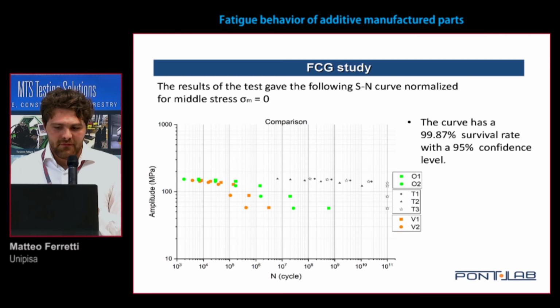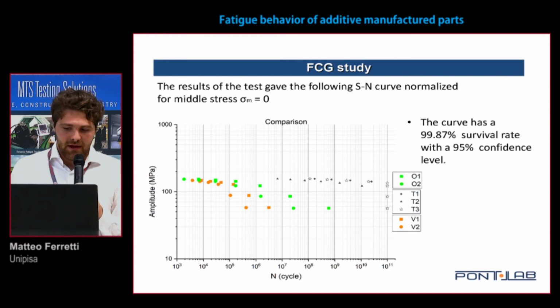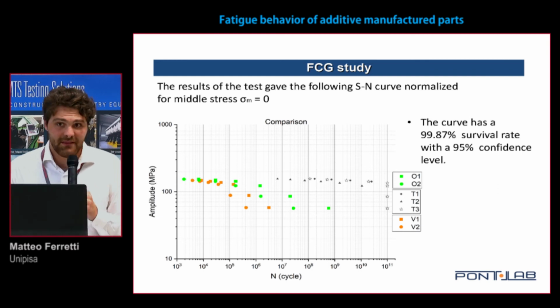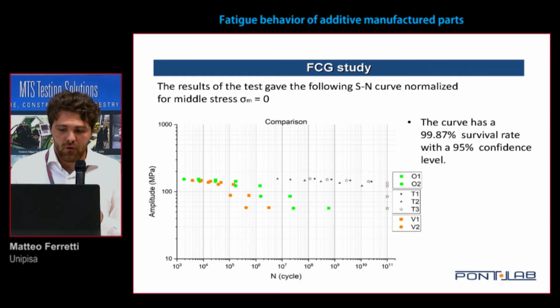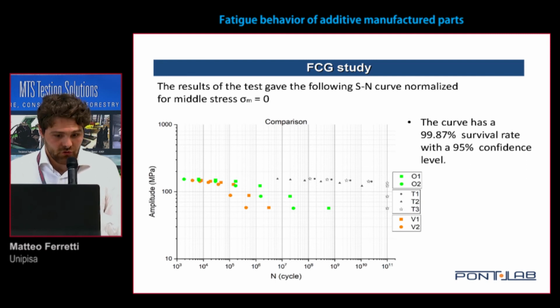The test gave the following SN curve, and this curve is for mean stress equal to 0, and in particular has a 99.87% survival rate and a 95% level of confidence. For this level of reliability, the amplitude was reduced following the normal distribution.